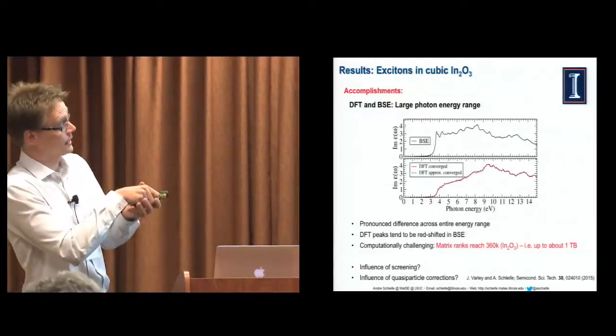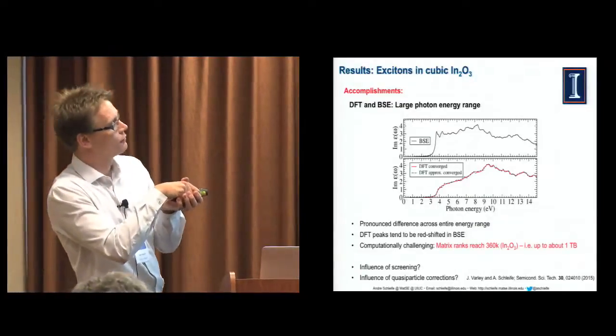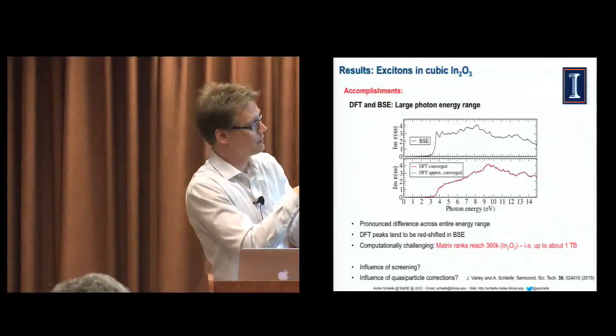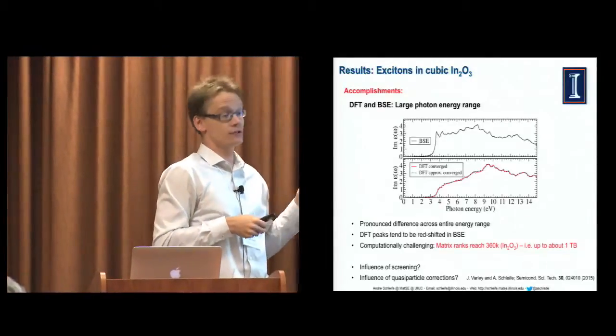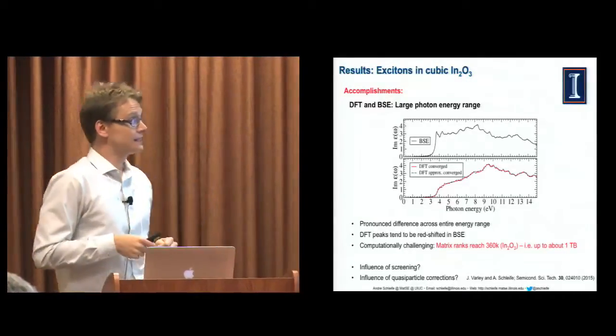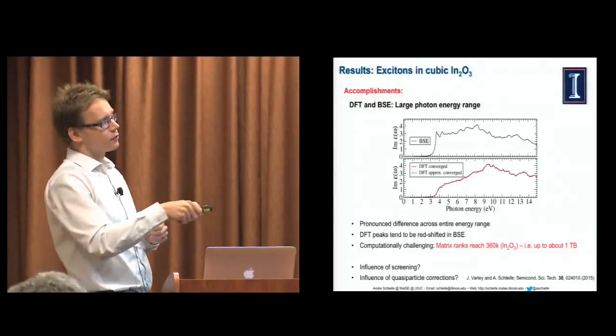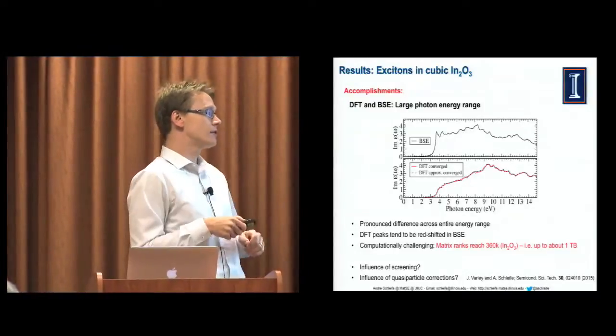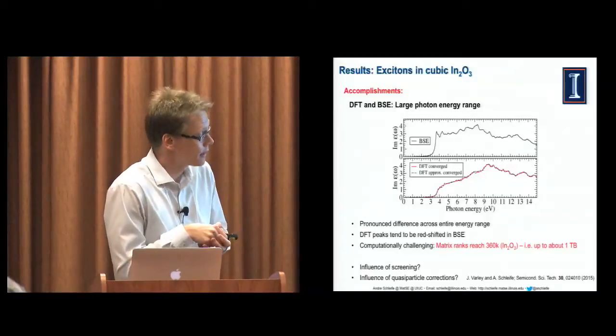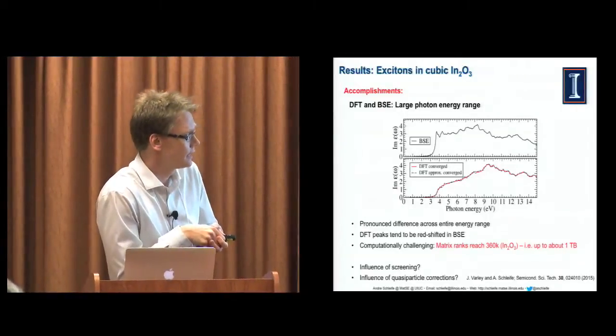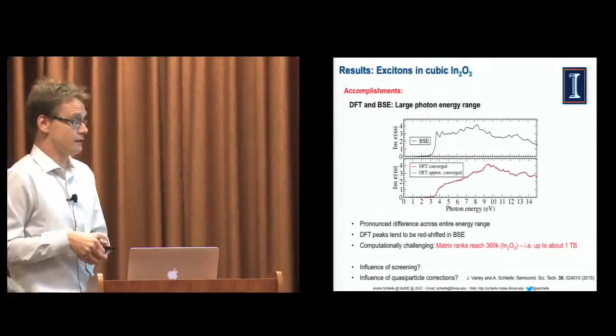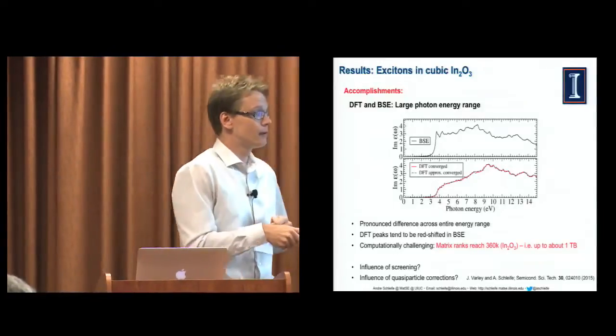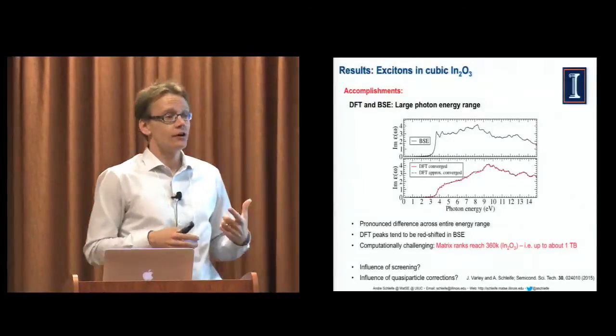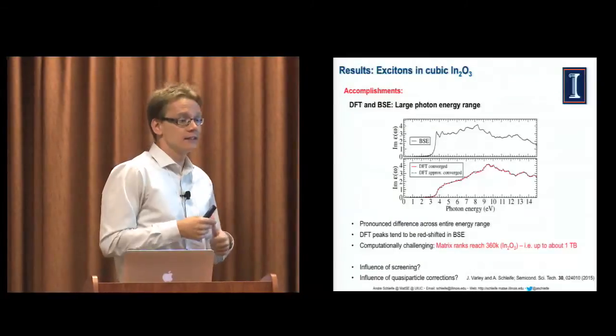Now, if you look at the same spectrum across a larger photon energy range, maybe from 0 to 15 eV, our experimental collaborators measured it from 0 to 40 eV, right? So that is really when it gets expensive, because in order to simulate a spectrum across such a large photon energy range, this matrix will be much larger. In this case for indium oxide, the rank of the matrix was on the order of 360,000. That is a matrix of about 1 terabyte. Now, that is hard to tackle, basically, and that is exactly why we use Blue Waters.